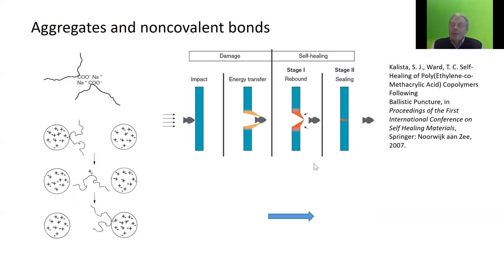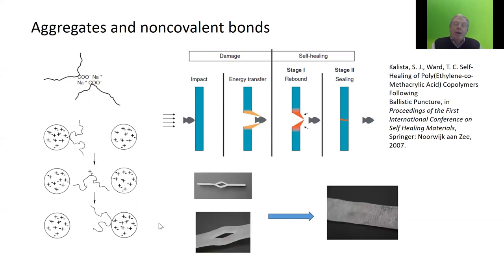But what it also can do, and that's quite remarkable, it's a beautiful self-healing material. If you shoot a bullet through it, the bullet forms a hole, but the hole closes after the bullet has passed and the material becomes dense again. Now, this self-healing process only works at the temperatures which the bullet creates while it goes through the material, so it works at very high temperature. And we are now working on making relatively large defects in the material and making sure that they close even at lower temperatures under well-defined conditions. And this is based on the ionomers. So this aggregation can be used.